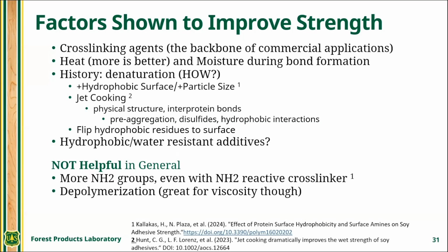We did a paper on jet cooking, which is when you take the protein in abundant water and inject steam. So you have a very high shear, high temperature environment. This makes very large insoluble aggregates, large as in tens or hundreds of microns in some cases. You very much change the way the proteins interact with each other. Physical structure, I think it develops interprotein bonds, aggregates them. You can create disulfides, create a lot of hydrophobic interactions between neighboring proteins to give you more structure.